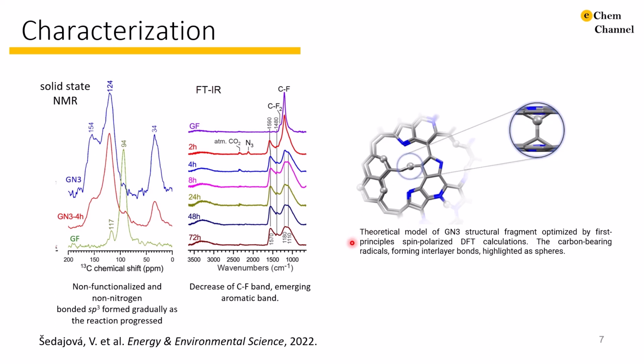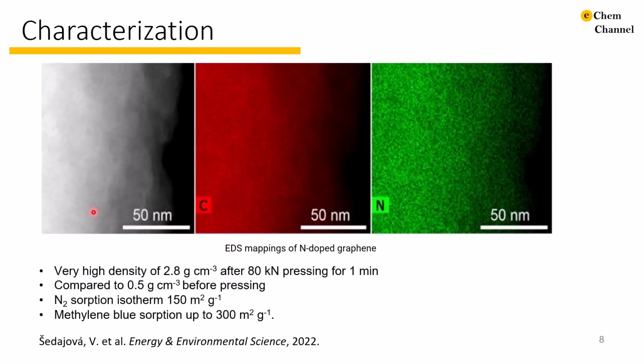Moreover, the theoretical model of a GN3 structural fragment, which was optimized by first-principles spin-polarized DFT calculations, shows the carbon-bearing radicals which were forming the interlayer bonds, highlighted here in spheres. Here, we can see that the GN3 sheets are really homogeneously and densely covered with nitrogen doping.